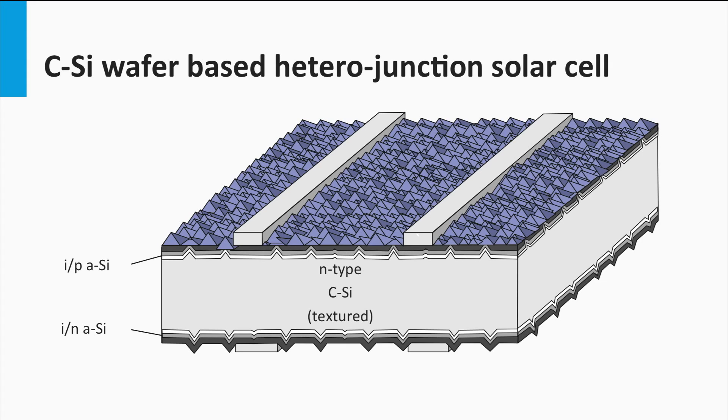The conductive properties of the P-doped amorphous silicon are relatively poor. In the homojunction solar cells the diffusion to the contacts takes place in the emitter layer. In contrast, in a HIT solar cell, this occurs through the transparent conductive oxide material, like ITO, which is deposited on top of the P-doped layer.